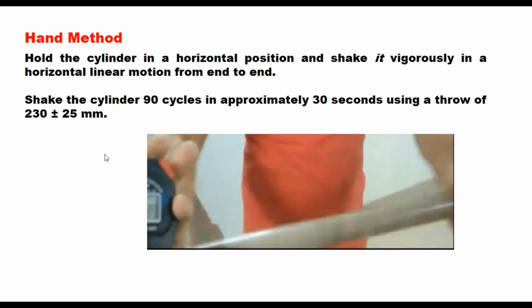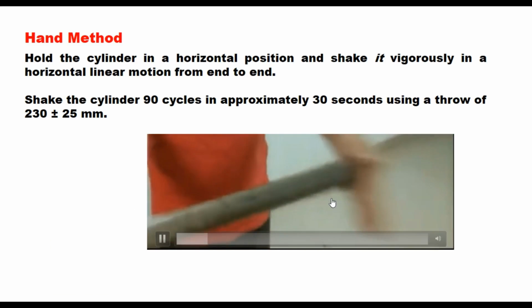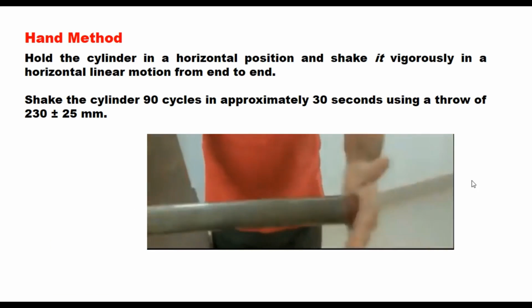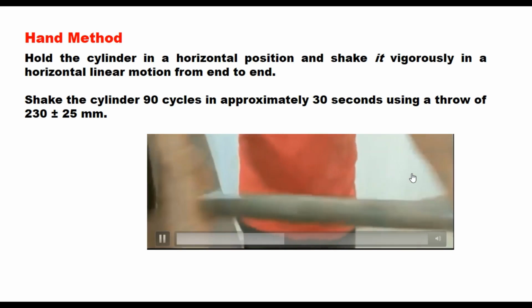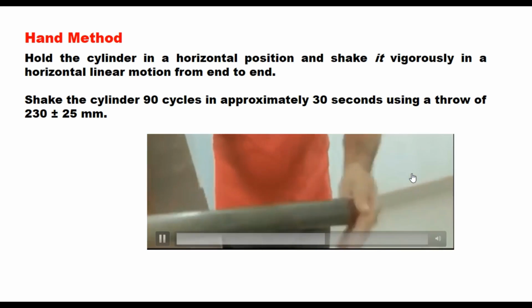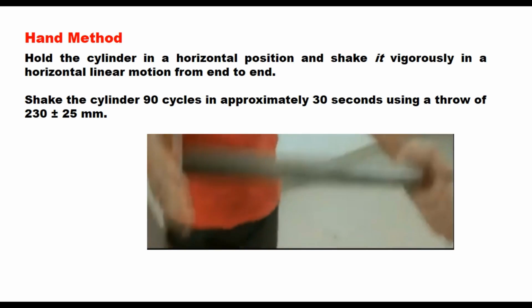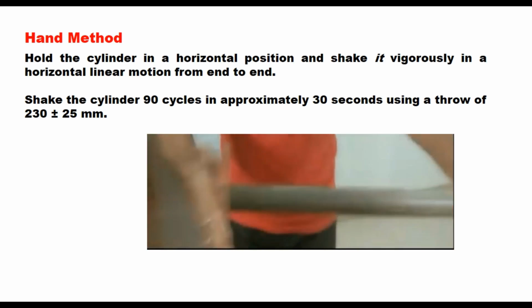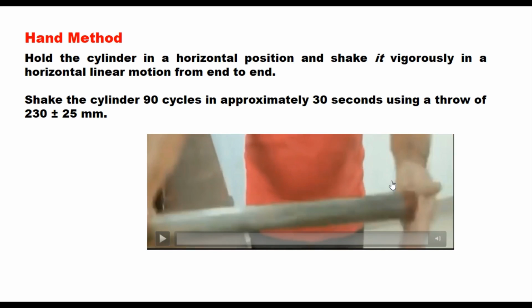It can also be done by hand, and in this case you hold the cylinder in a horizontal position and shake it vigorously in a horizontal linear motion from end to end. Shake the cylinder 90 cycles in approximately 30 seconds using a throw of 230 plus minus 25 millimeter.